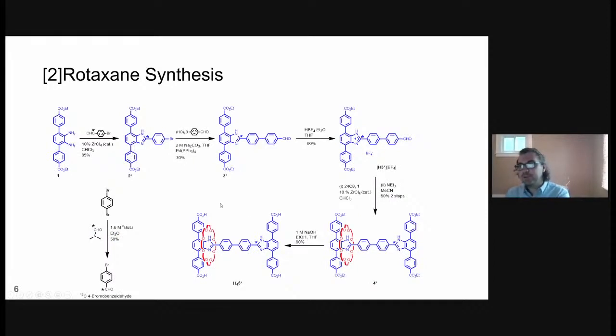I'm not going to spend too much time on this organic synthesis, this being the MOF conference. The main reason I have this here is to point out the fact that in these ligands, we enrich one position of the benzimidazole recognition site with carbon-13. We can do this reasonably easily, starting with carbon-13 enriched dimethylformamide. The reason why we need to carbon-13 enrich this position is so we can get sufficient signal in the carbon-13 solid-state NMR to work out basically what the ring is doing, as the chemical shift of this carbon here is very sensitive to whether it's free, or in this case binding the crown ether macrocycle.